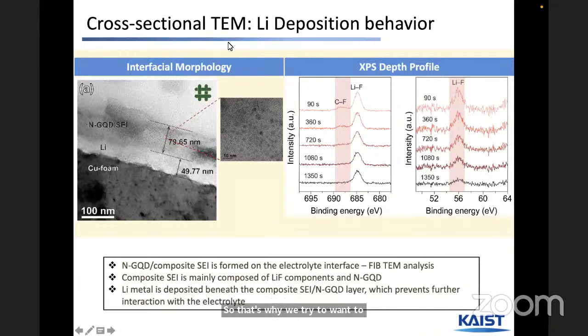Okay, in the elemental mapping, you can see the copper and the lithium here. Then we want to see a cross-sectional image. This is a triangle side, inside is empty, this is copper. On the surface of the copper, you have carbon and nitrogen. Lithium is probably deposited beneath the GQD layers in the SEM observation, but it's not very clear. So that's why we cross-sectioned the material to see it in STEM.